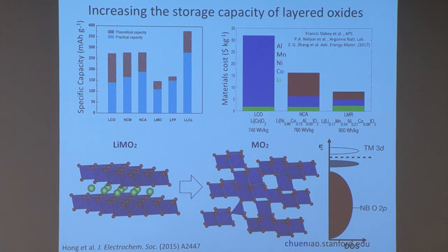So as you remove a lot of lithium, you're actually putting the material in a very oxidized state. And eventually, from an electronic structure perspective, the Fermi level goes down so much, it begins to empty your non-bonding oxygen state. And this essentially destabilizes the oxygen, and the oxygen comes out. This is both a problem for performance, because you will start to further rearrange the material, and two, it becomes an oxygen source, which presents a safety hazard.